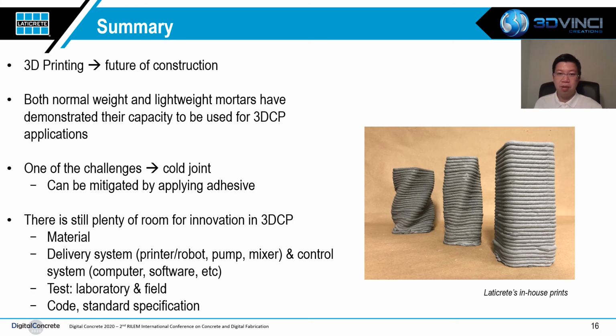The normal weight can be used in most regions of the globe, while the current lightweight is suggested only to be used in areas where winter is not part of the season. Regarding the cold joint, indeed it is a weak point, especially in tension. However, the interlayer adhesion of the cold joint can be improved by applying an adhesive between the layers.